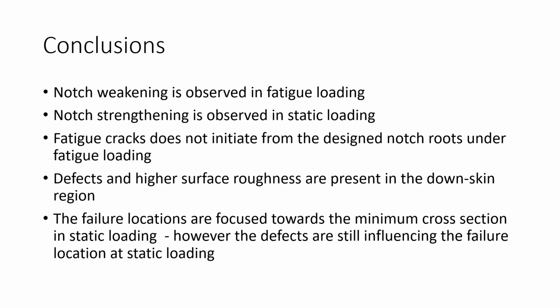Okay, so conclusions. Notched weakening is observed in fatigue loading, and the strengthening is observed in static loading. Fatigue cracks do not initiate from the designed notch root under fatigue loading, but from defects. And the defects and higher surface roughness are present in the downskin region, causing this. And the failure locations are focused towards the minimum cross-section in static loading. However, the defects are still influencing the failure location at static loading.